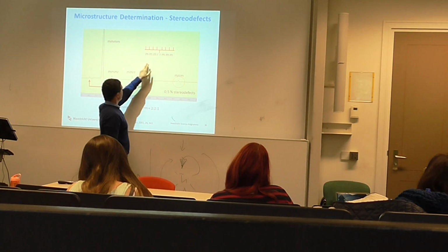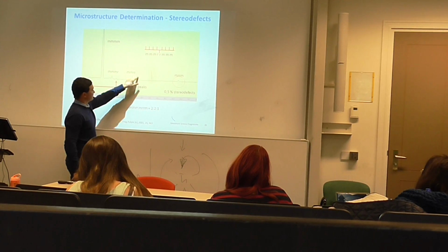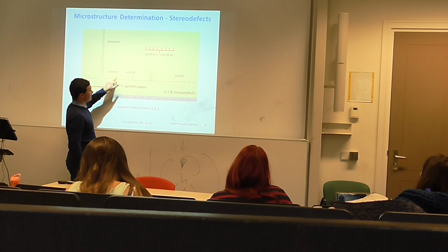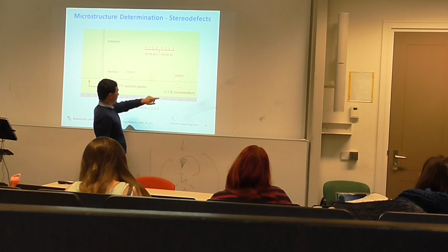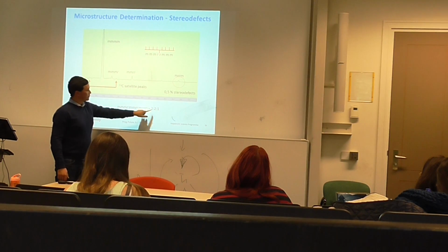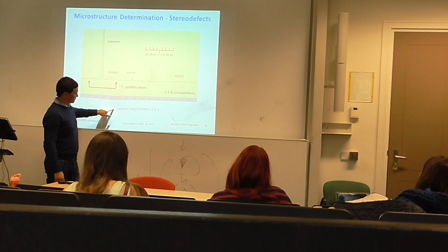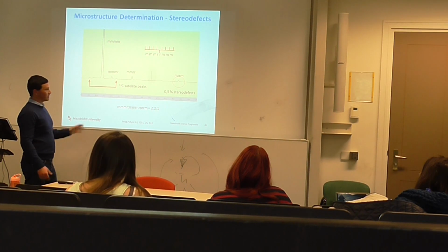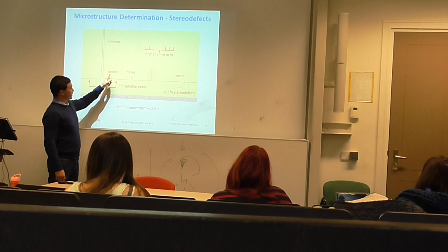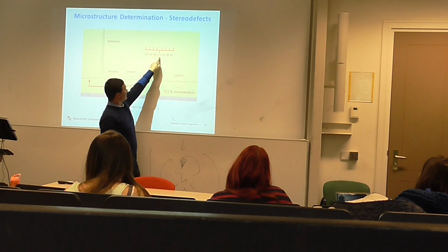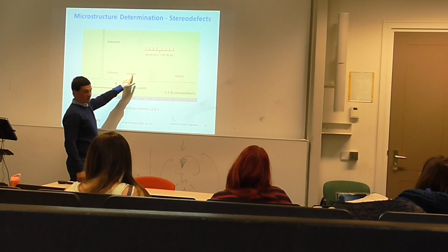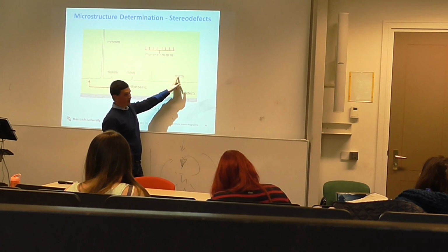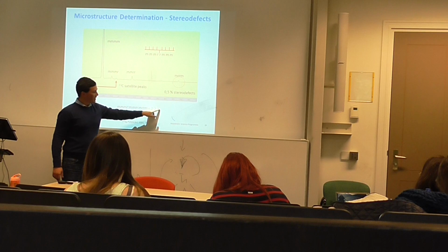So you can have the string of MMRR, which is this one, the string of 3M and 1R, this one, and MRRM, in a ratio 2 to 1 about these strings. Why 2 to 1? This is asymmetric, so it can be 3M, 1R, or 1R and 3M. This is also asymmetric, so MMRR or RRMM, and this is symmetric, so it's going to be only MRRM. That's the reason why the ratio between them is 2 to 1.